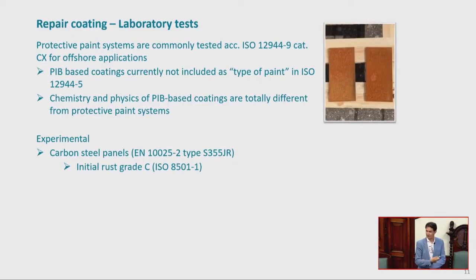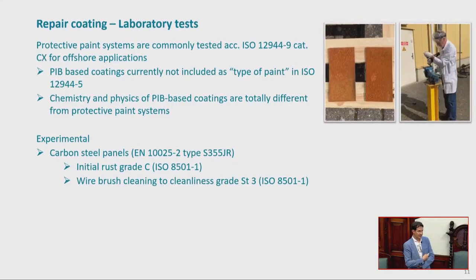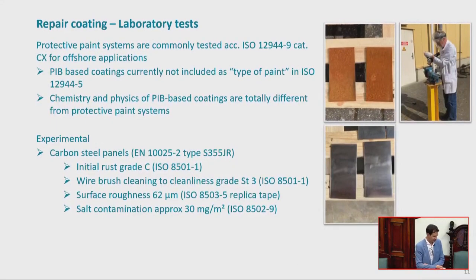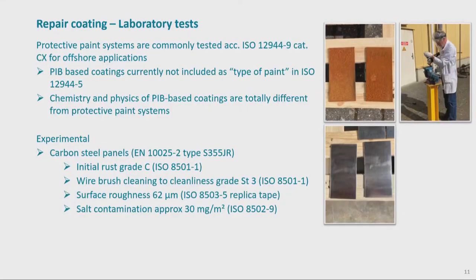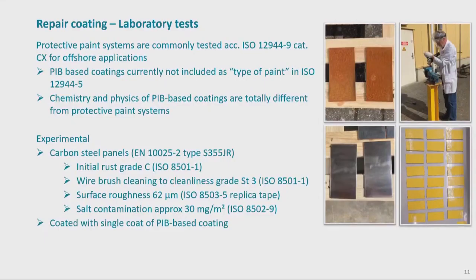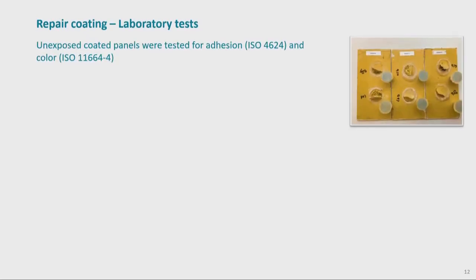Because you prepare carbon steel plates, you remove them. Now, like I said, because of the adhesion mechanism of this material, you can get away with minimum surface preparation. Remove loose rust, loose paint, and just put it on. So you don't need a roughness as such. And therefore, a lot of the tests that we do are on that minimum surface preparation. So rather than SA2.5 with roughness or without roughness, if we just stick to the cleanliness method, we try to do as much as possible because it is a repair coating on purely mechanically prepared surfaces. And of course, we take care that you pass all these requirements in the standards, so we do everything right. Prepare the patches, we've got them in, and then throw them into the lab. And then we go through the testing.